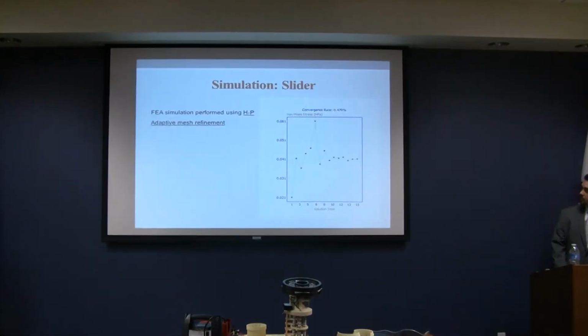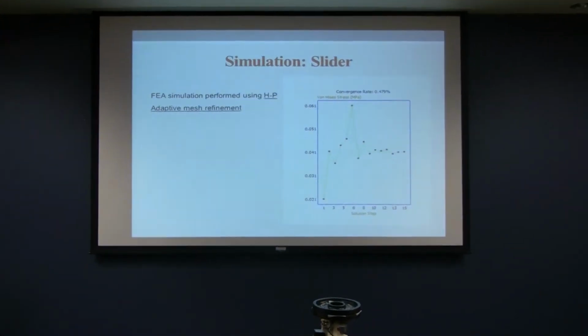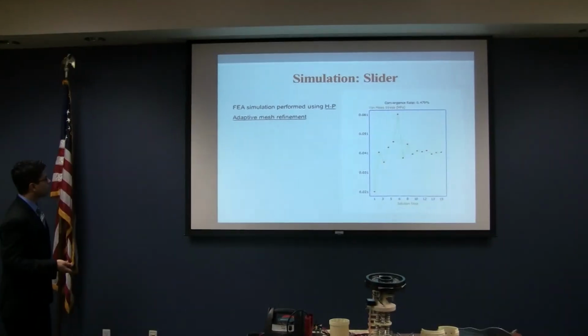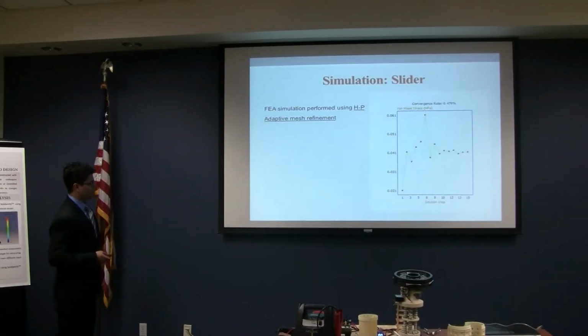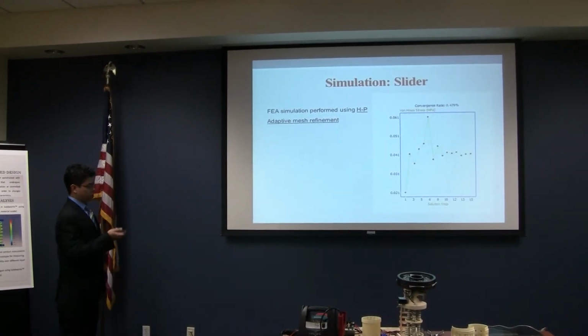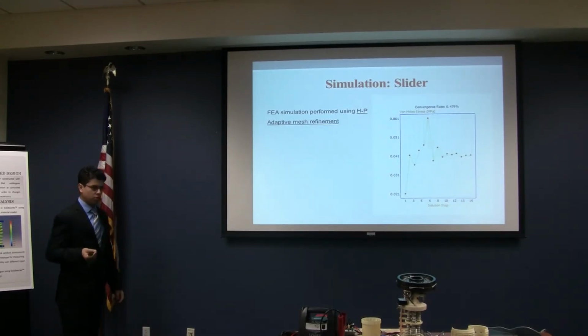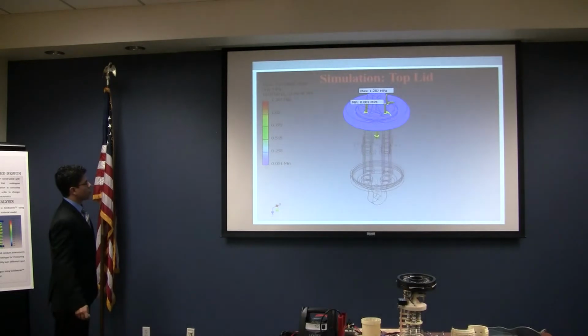So we performed the convergence rates to show that the analysis is good. We use adaptive mesh refinement, which changes the mesh size in order to converge to a solution. This is the top lid. We found the von Mises stresses.